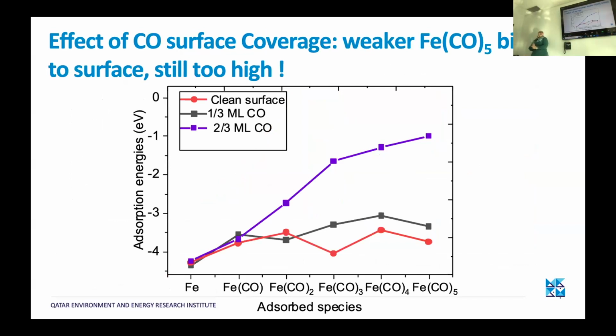So we did that. We looked again at the energetics. We looked at the adsorption energy of each of the species. What we see a priori is that the adsorption energy is really very strong for each of the species if we are dealing with a clean surface. If we increase the coverage to 1/3 monolayer, it increases a little bit. But when we take it to 2/3 monolayers of CO, it has a very good increase. But this still cannot explain that we would be able to completely desorb any of these carbonyls, even with this binding energy. So it was really puzzling and it was like a dead end for us.